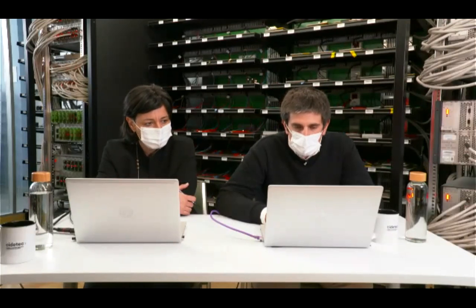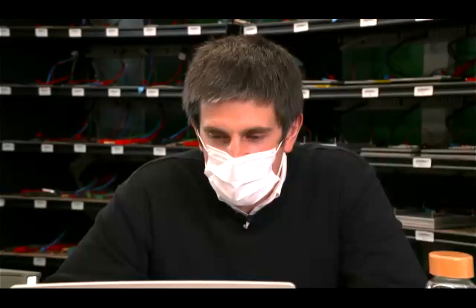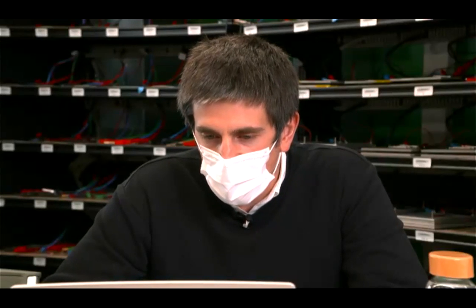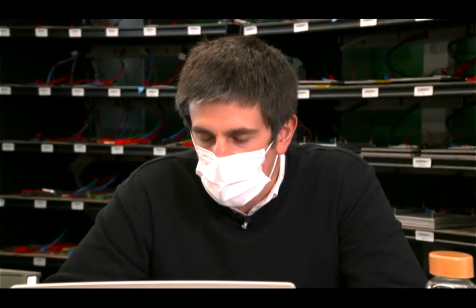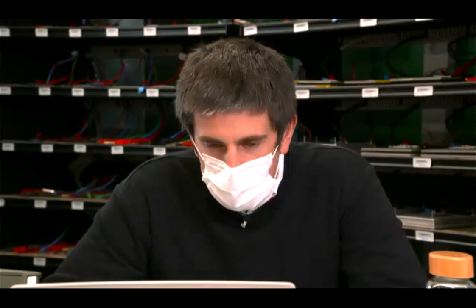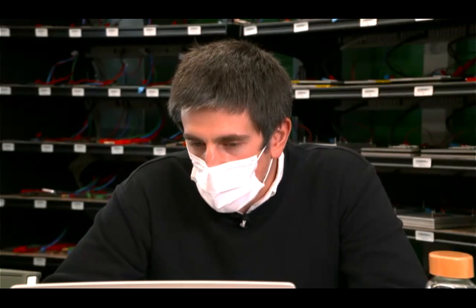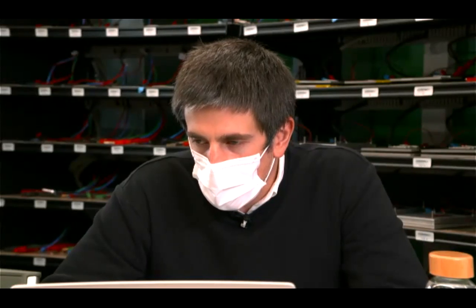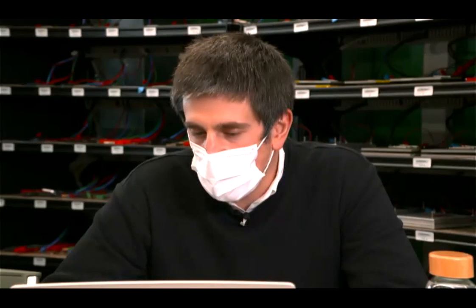Usually, when you are doing a set of cells, the difference between the voltages and the internal resistance is very low. So it can give us a clue if we have a problem in one specific cell, if the values of voltage or internal resistance are coming from a problem inside the cell. In order to do that, as is said in some questions, impedance spectroscopy can play a very important role, because if you measure the resistance of the cell with the multimeter, you have the value, but you don't know the reasons behind this high internal resistance. With impedance spectroscopy, we are able to see if there is any part or interface that is enhancing this growth of the internal resistance.